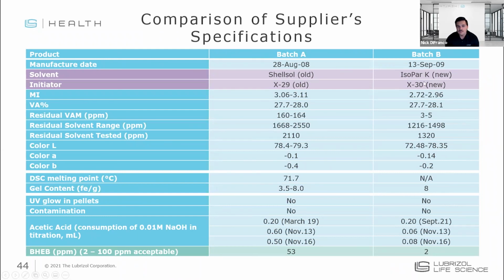Here's the new solvent and initiator in the process. Specifications weren't significantly different, but what we found was that right at the bottom here in green, there was a wide range in the specification for antioxidant in the polymer. From 2 to 100 parts per million was considered within spec, acceptable.